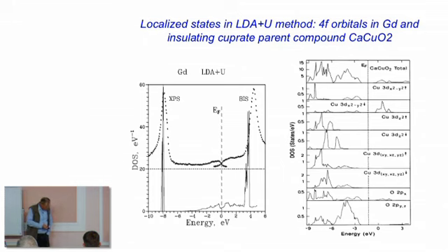Now, the simplest approximation, which moves down occupied and up unoccupied states, gave us very good agreement for spectra, photoelectron spectra and inverse photoemission spectra. So it not only split them, it moves bands to the correct position, which is important. So that is for completely localized F states.